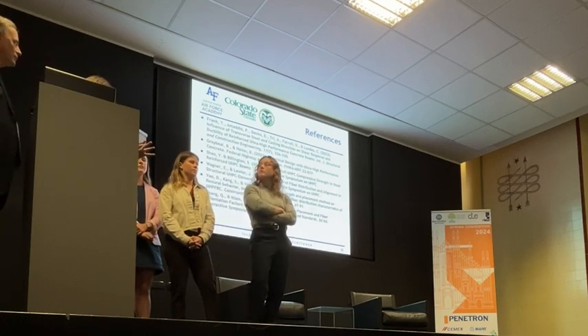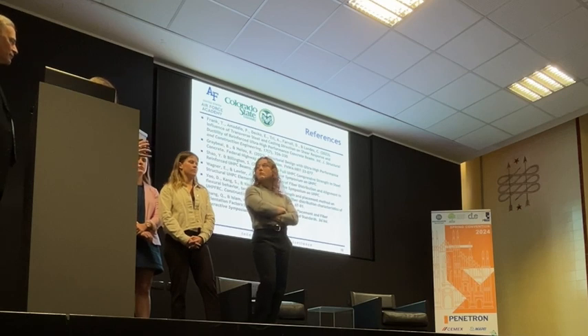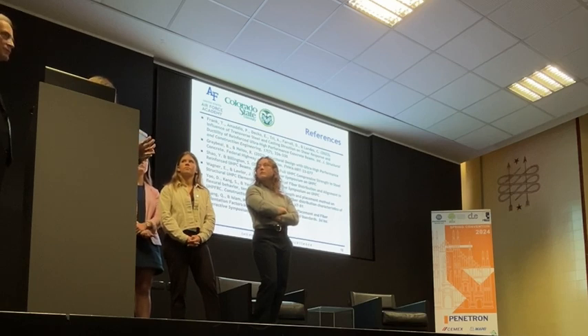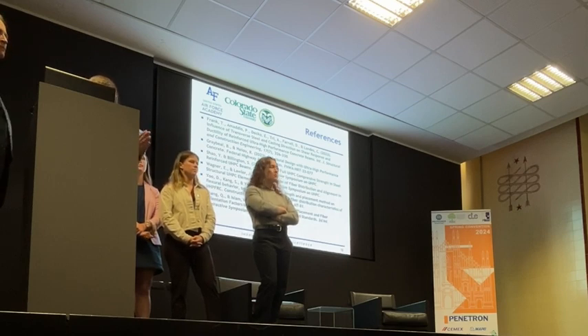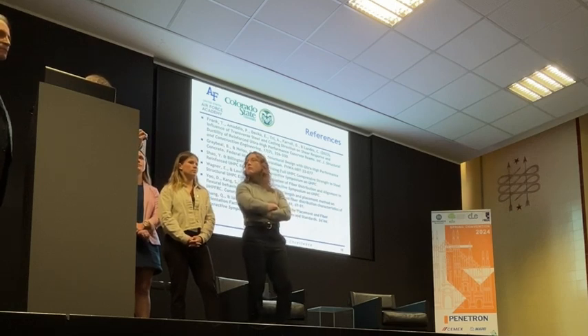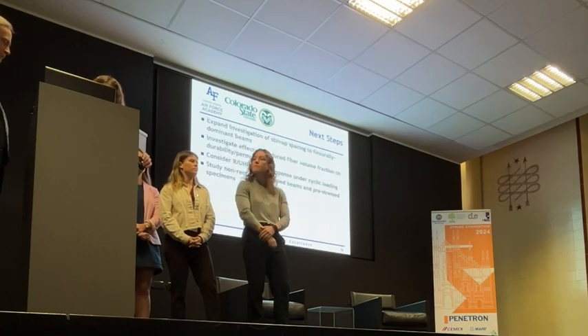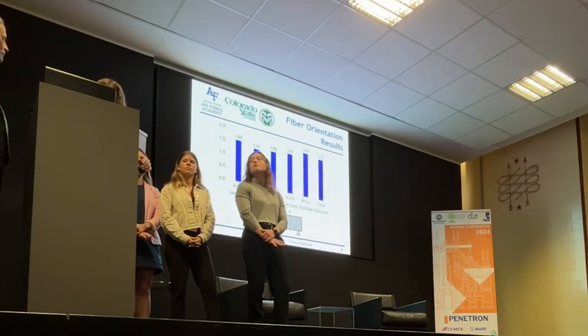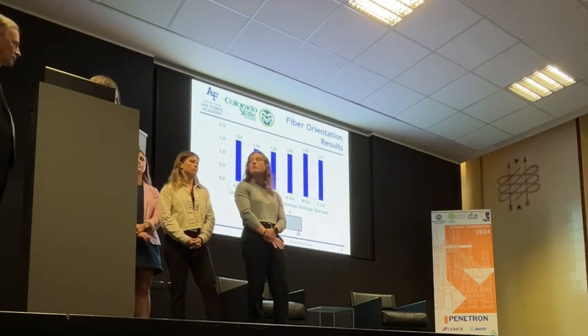What we did, we imaged those cross sections, and then MATLAB converted those images to grayscale. Because we used light to image them, the steel fibers being metallic, they're shining, they reflect that light, and the concrete doesn't. So when it converts to grayscale, all the concrete becomes black and all the steel fibers become white. MATLAB takes all of those white areas and draws an elliptical shape around each, automatically calculates the major axis divided by the minor axis, takes the average of all of those numbers, and that's exactly what you saw when we had 1.59, 1.44. That's the average of every steel fiber that it sees in that grayscale image. Okay, so very nice. Thank you.